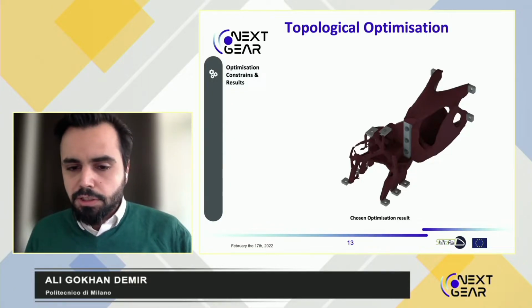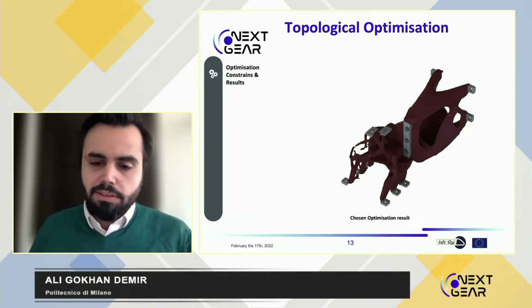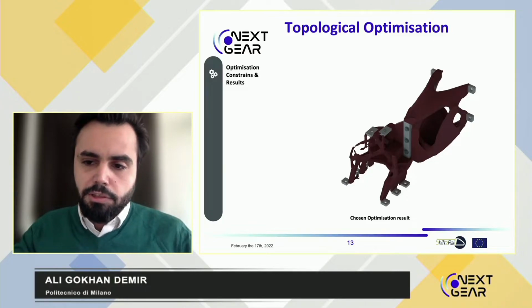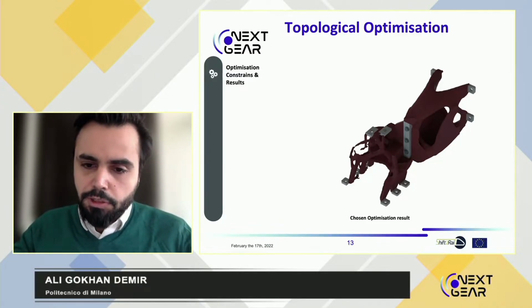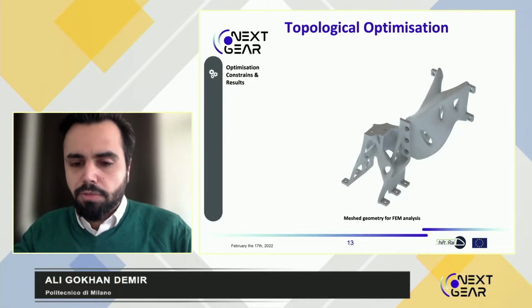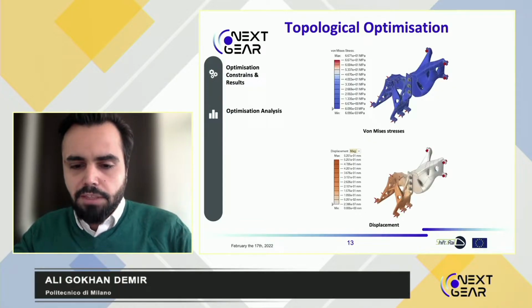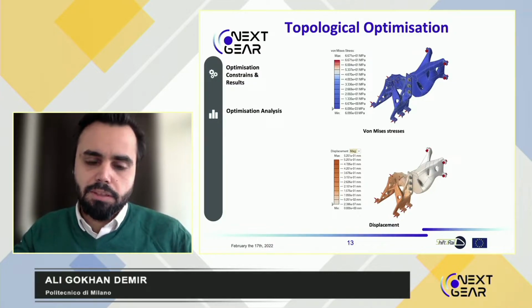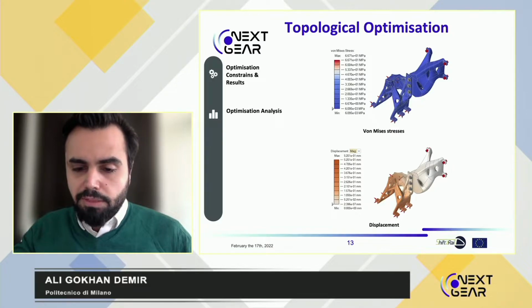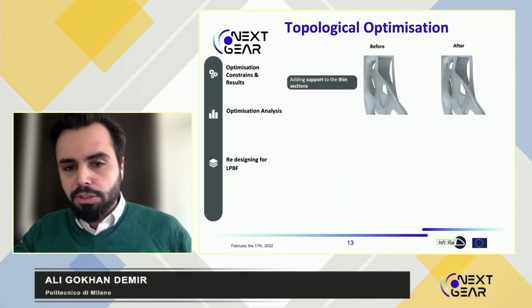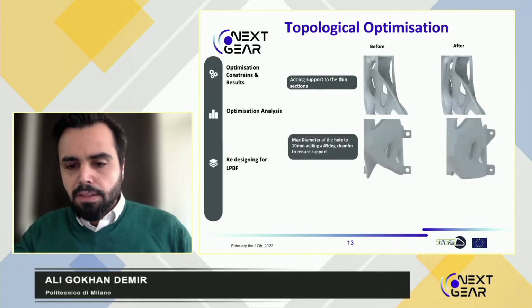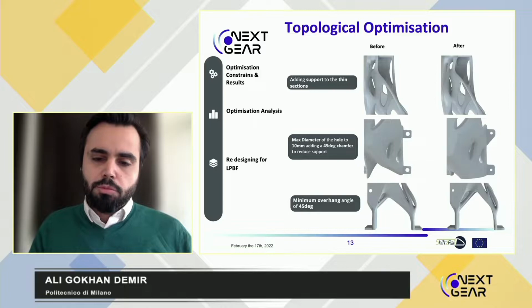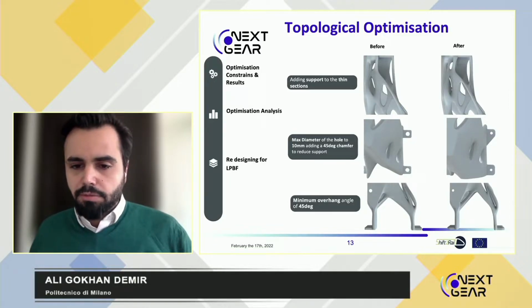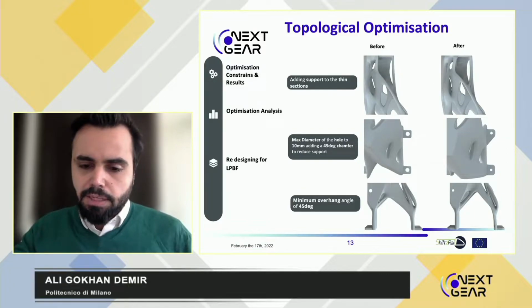Now, topological optimization matches very nicely with laser powder bed fusion, but as you see, the optimization results are not really optimal for production. So we had to also go on with the design, do modifications, and the final design was once again tested in finite element modeling, allowing us to see that we maintain stiffness and reduced the weight quite significantly. Last but not least, the part was supposed to be also modified for manufacturability by laser powder bed fusion. We did some basic modifications in order to make the part producible as fast as possible.